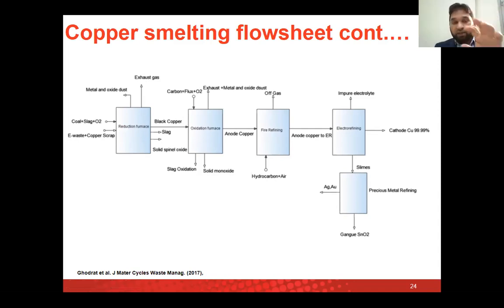Now we will try to understand that one. First is the reduction process, the second one is the oxidation process. In the oxidation process, we add carbon, flux, and oxygen. And during this process, what happens? We have the slag oxidation, a slag that is produced during the oxidation process. We have some solid monoxide, and then the purity of the copper is increased to more than 99%. That kind of copper is called the anode copper. Then we do the fire refining and electro refining, and from electro refining you get the cathode copper, and then slimes, as I mentioned earlier.